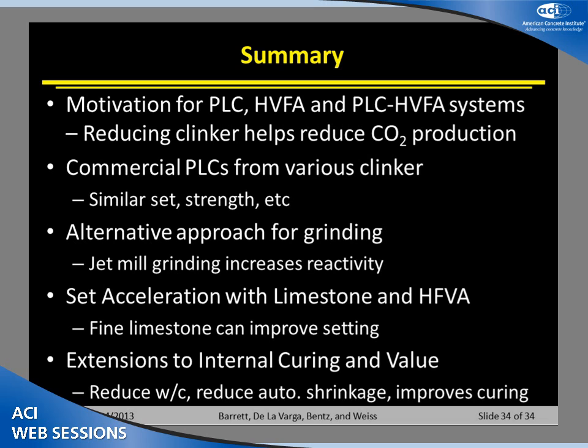One of the things that I would actually put out, maybe as a teaser: we spend a lot of time focused on can we air entrain the concrete, and I would argue that we could spend as much time asking, can we make concrete freeze-thaw resistant using a different mousetrap? I think there's a lot of value in there because all of a sudden we get away from some of these problems, especially when we get to fly ash systems. Can we use a sealer? Can we use an internal waterproofer? If you can keep the water out of the system, you can make it freeze-thaw resistant.